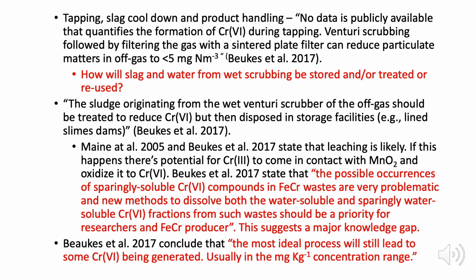And a lot of this information comes from Beukes et al. 2017, who state that leaching is likely. If this happens, there's potential for chromium-3 to come into contact with manganese oxide and oxidize to chromium-6. Beukes et al. also state that the possible occurrences of sparingly soluble chromium-6 compounds in ferrochrome wastes are very problematic, and new methods to dissolve both the water-soluble and sparingly water-soluble chromium-6 fractions from such wastes should be a priority for researchers and the ferrochrome producer.